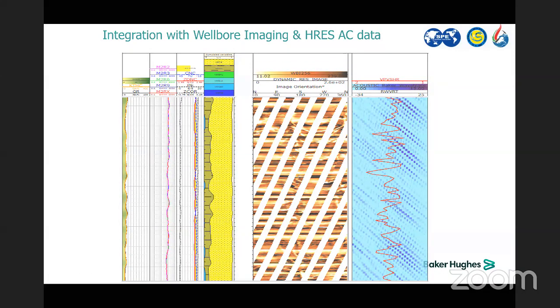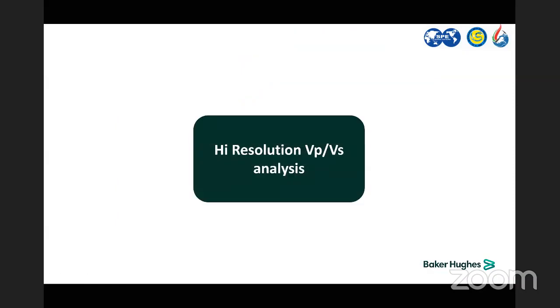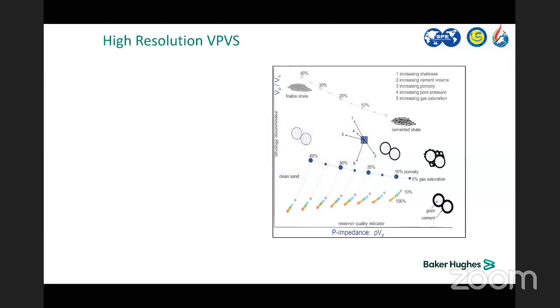So this will help you get a high resolution for the density neutron and acoustic. You can use both of them as inputs in your multi-min or in your shale sand or sand laminated model to enhance your porosity calculation with this high resolution. One of the interpretations is the high resolution VPVS. So if we enhance the compression and shear, you can get from the high resolution 6-inch VPVS,